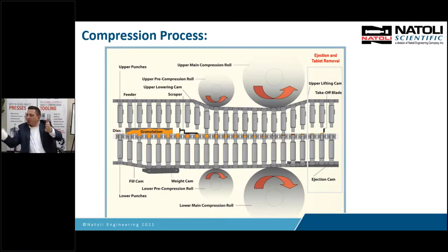So as this punch comes around, it hits the takeoff bar. This is where we see sticking problems and picking problems. Sticking is when the powder starts to adhere to the punch face. Picking is associated with when you have a logo or embossing and you have material between the crevices, like a zero, the land, or certain numbers, like eights, will cause picking issues. That's the takeoff stage. So if you have an ejection issue, you address it differently than a takeoff issue.